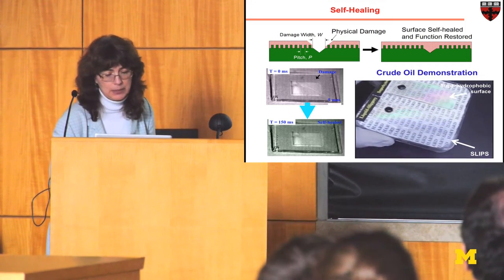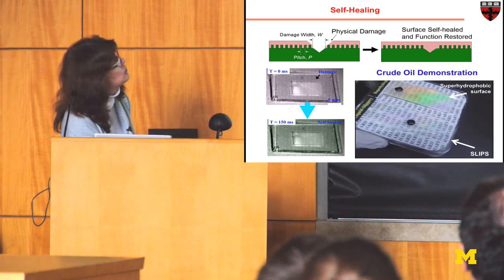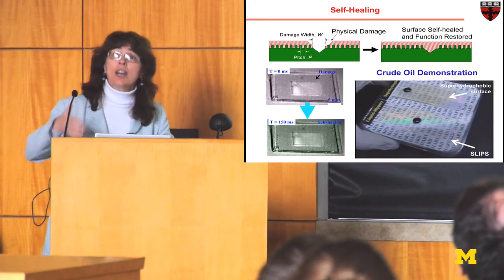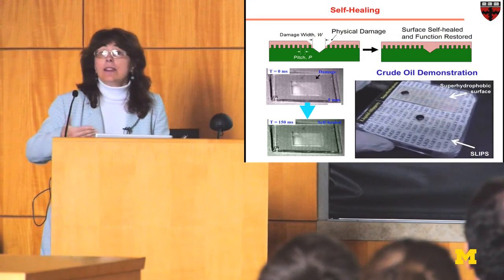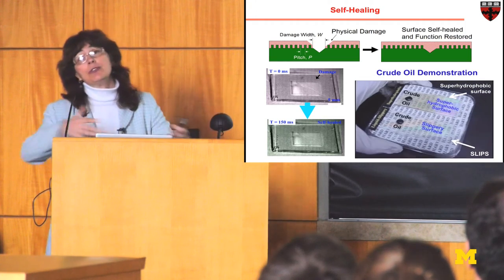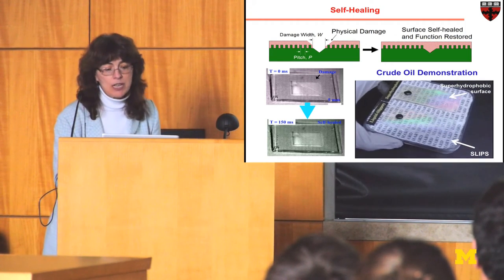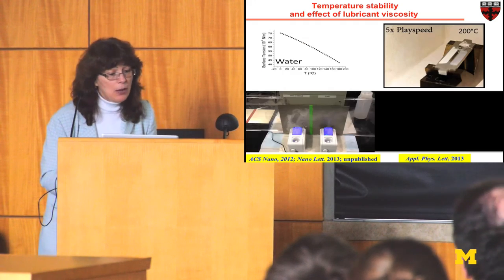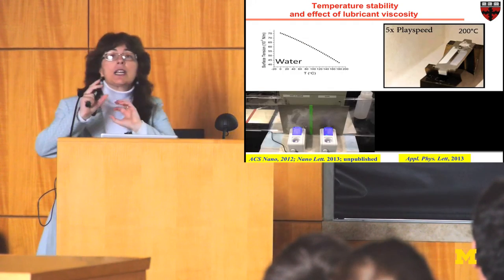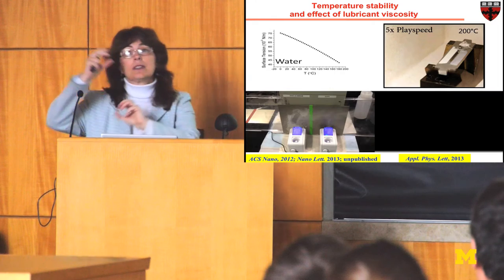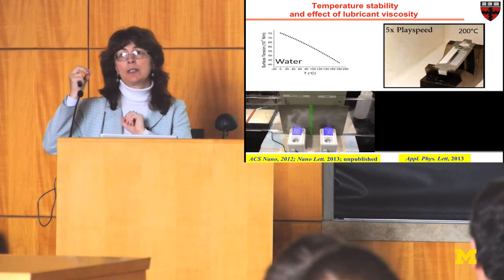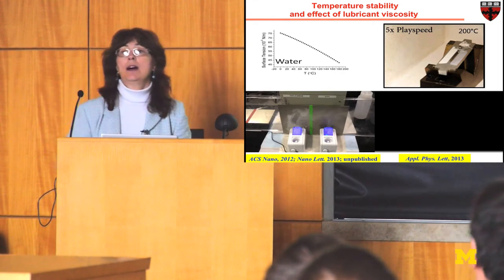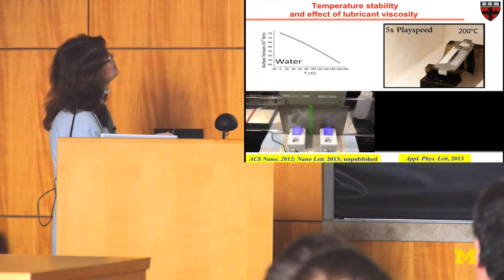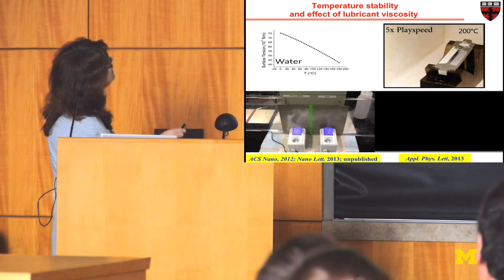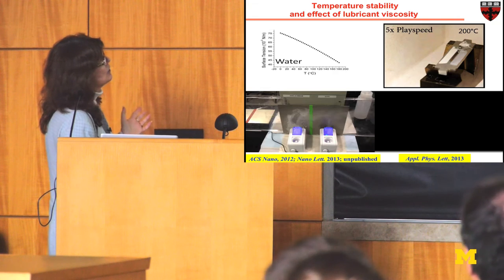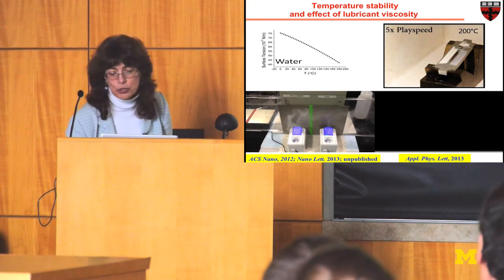This is an amazing ability, and it's due to the ability of liquid to reconfigure on the surface. When you cut it, you create even more roughness, and liquid likes this surface, so it will redistribute again and recreate a slippery surface. But now, since it's designed of three components, the roughness, the liquid that you use as a slippery liquid, but also how to match the chemistry between themselves, one can think about high temperature or low temperature conditions and design the system that works anyway.